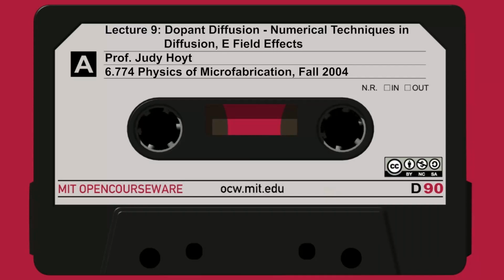And we then can write in for the flux. The flux is just the diffusivity D times the concentration difference across that plane. Across plane R, the concentration difference is C1 minus C0 divided by delta x. So we can approximate it that way. That's the flux crossing plane R. What's the flux crossing plane S? Well, we can do the exact same thing for the number of atoms crossing plane S. It's just the diffusivity times delta t times, this time, C2 minus C1 over delta x.